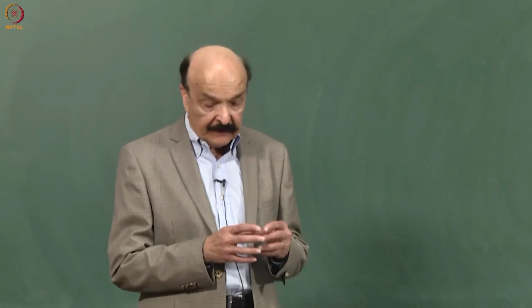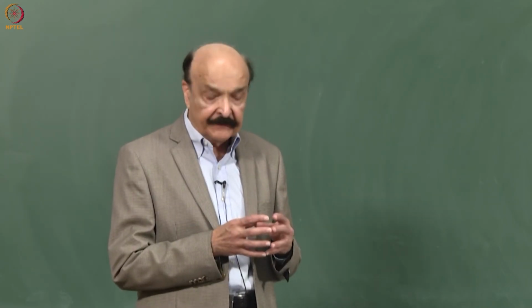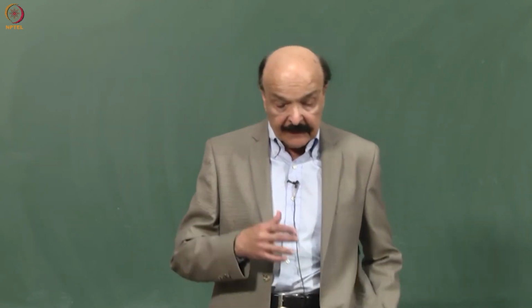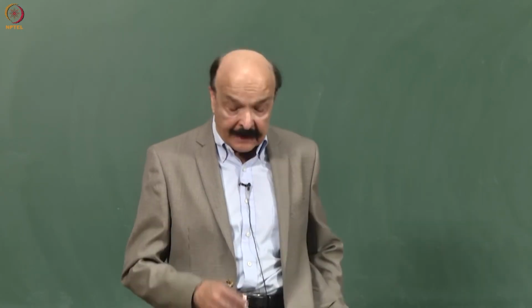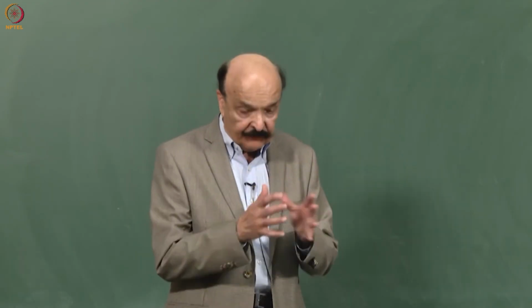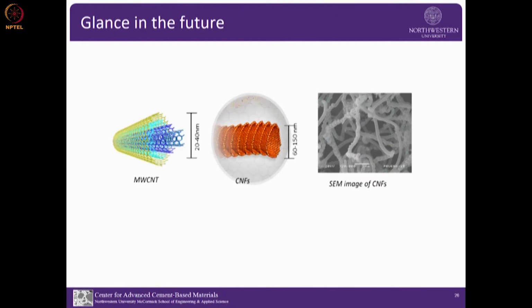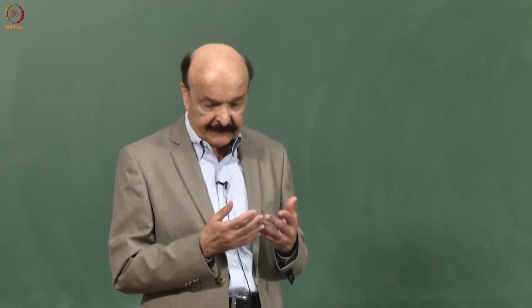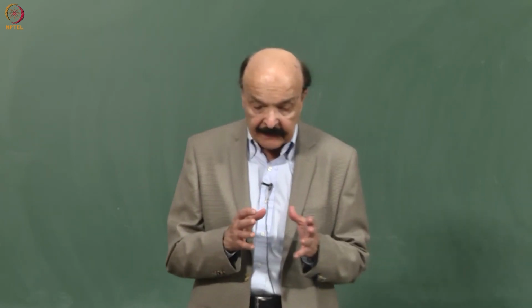So I'm pointing this out: with the development of rheology and fibers, we can produce both strain hardening composite with relatively large strain and high compressive strength. This is where we are as far as microfibers and macrofibers. We have conventional fiber reinforced concrete, where a lot of work has been done on what happens in cracked concrete with time, in creep. And UHPC, very high strength concrete up to 200 megapascal and 3 to 4% of fibers. For example, Lafarge has developed a product they call Ductal, which is the same idea, and now UHPC has been used in many applications.